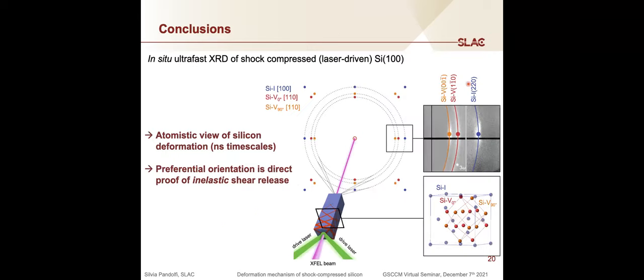So just to quickly summarize, using ultra-fast X-ray diffraction with laser-driven shock compression of single crystalline silicon, we have been able to observe and quantitatively study the orientation and the microstructure evolution of our sample and link this with a very specific deformation mechanism. And so we're able to provide an atomistic view of silicon deformation mechanism at this nanosecond timescale. And because of the strongly preferred orientation, we have been able to link this with the specific inelastic shear release mechanism that seems to be peculiar only to the ultra-fast timescale of laser-driven shock compression, as opposed to what happens at lower strain rates for gas gun-based shock compression.